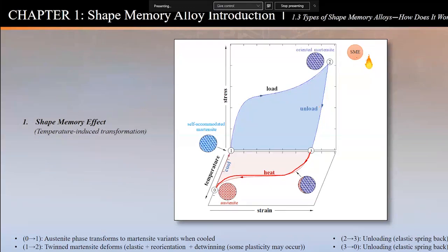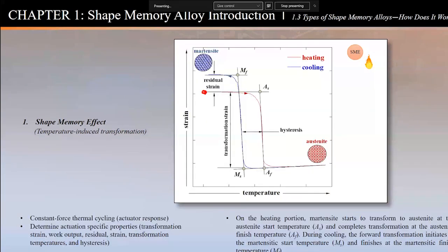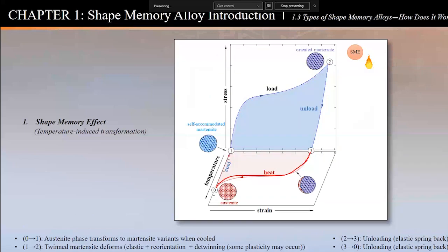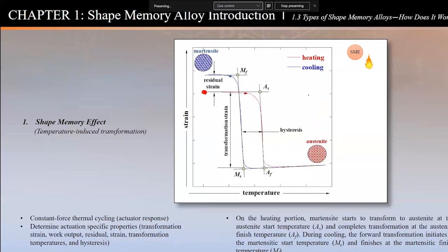Okay. Now, in the shape memory effect, if I take this plot here, this bottom curve, and I just look at the 2D, forget about the 3D plot now. Now let's start at room temperature right here. I'm right here. Now I start heating under a load. Now I take a piece of metal, I apply a load to it, 2, and I don't unload. I stay at 2. So this is fully loaded metal or components, and then I heat. As I heat, I go this way, and then I generate quite a bit of displacement. Okay, where is it going? It's going to the austenite parent phase, and when I cool,